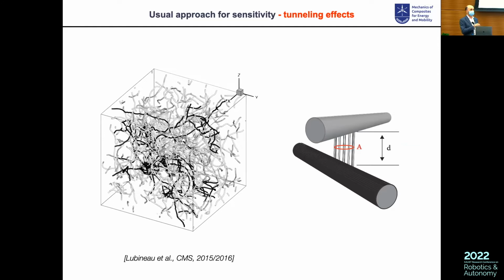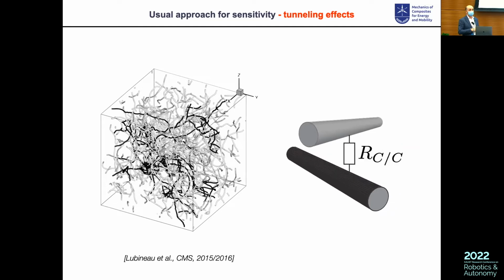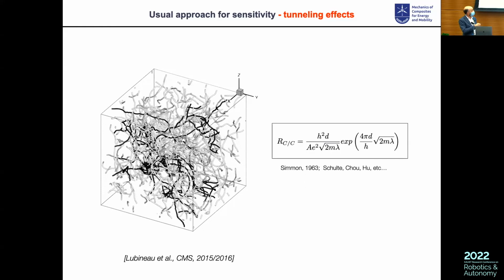What you assume is that at the junction between the particles, to make it simple, there is a kind of equivalent resistance. Of course, it's an oversimplification, but you can assume this resistance is exponential with respect to the distance between the particles. That means as soon as you separate the particles a little bit, the resistance is going to increase a lot. This is what gives the geometrical perturbation of your network. It is what gives the piezo-resistivity, right?